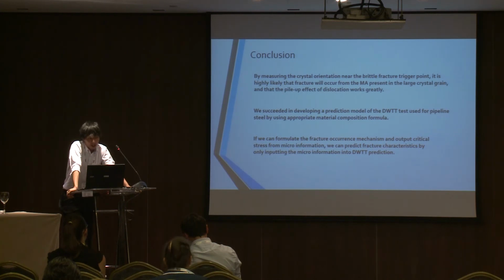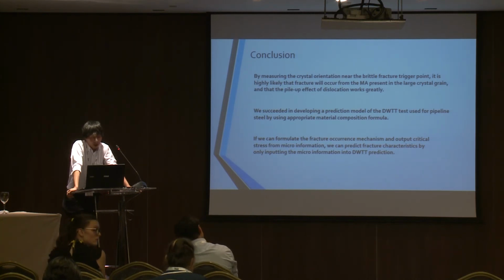Finally, I'll present a summary of this research. By measuring the crystal orientation near the brittle fracture trigger point, it's highly likely that fracture will occur from the MA present in the large crystal grain, and that the pile-up effect of dislocations works greatly. And we succeeded in developing a prediction model of the DWTT test used for pipeline steel by using an appropriate material composition formula.